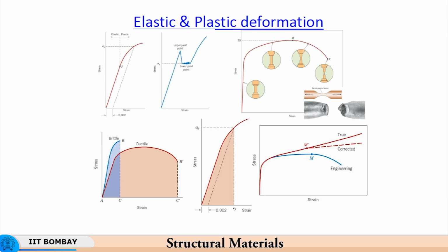So, that is why you see that the material is becoming harder and harder, the stress is increasing. So, the stress required to deform the material is continuously increasing. Put in other words, the yield point of the material is continuously increasing. So, if you were to, let us say, unload this material from this strain level, then you would have to stress it to this stress level before it can yield.